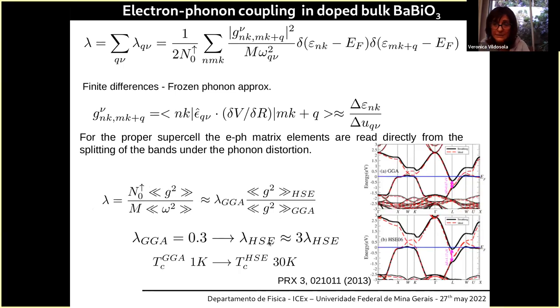Gabi Kotliar and his team demonstrate that when you calculate it with GGA, you have an electron-phonon coupling that is around 0.3. And with this electron-phonon coupling, the superconducting critical temperature would be around 1 Kelvin. And if you calculate the electron-phonon coupling with this hybrid functional, you observe here that the shift in the energy levels is almost 3 times the one that is observed here. And they show that they can explain the 30 Kelvins with this hybrid functional.